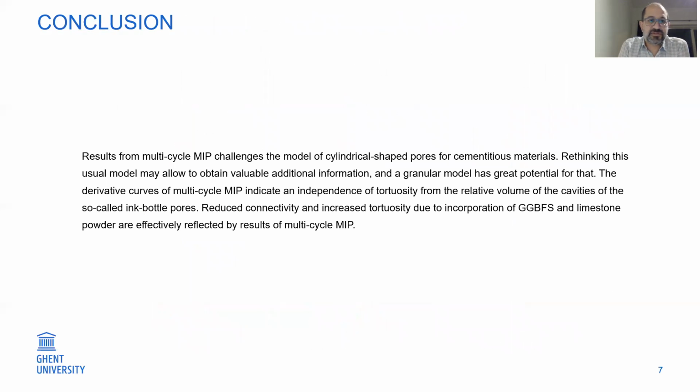So our conclusions are that the results from multi-cycle MIP challenge the model of cylindrical shape pores for cementitious materials, and rethinking a model, probably the granular model, might allow us to have more profit from this technique.